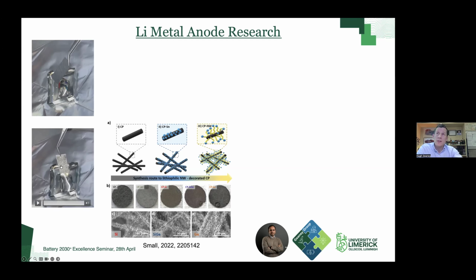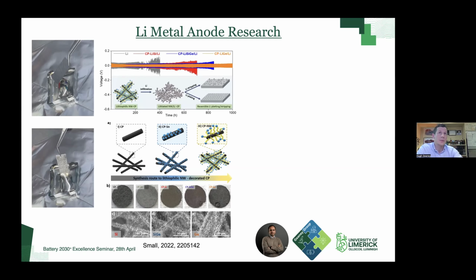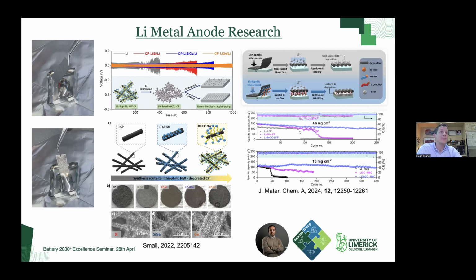What I would say with these is that they're reasonably thick, and the amount of lithium that is incorporated is extremely large. If you were to electrochemically strip out that lithium, it's in excess of 30 milliamp hours per centimeter squared. With those architectures, we examined, as a function of the nanowire composition, the reversibility of stripping and plating. In this case, germanium was the outstanding performer. You can see that it maintains the longest reversibility, followed by these silicon germanium alloy materials, then silicon at the end, and this is our control lithium here.